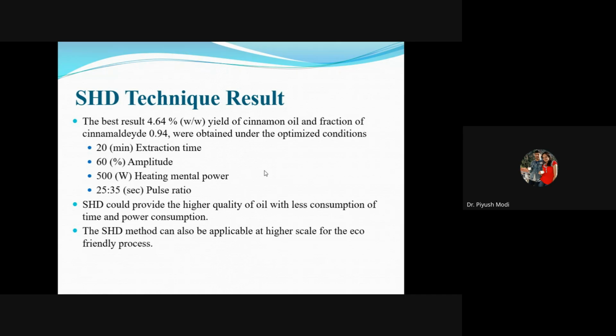The optimum conditions are 20 minutes, 60% amplitude, and 500-watt heating, because we run both the heating mantle power and the ultrasonic together, with a 25 to 35 second pulse ratio. So we get the oil this way. You can see the result of the SHD technique.